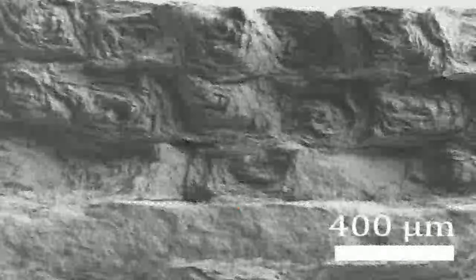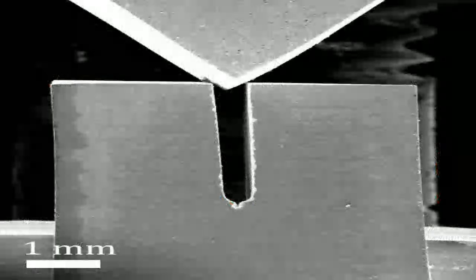In a silicon carbide matrix, using boron carbide as an additive, the boron acted as a catalyst that graphitized the carbon fibers, essentially messing up their structure and properties. They confirmed this using analysis techniques like Raman spectroscopy.